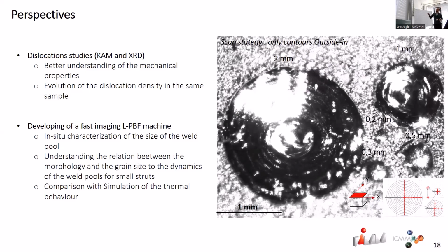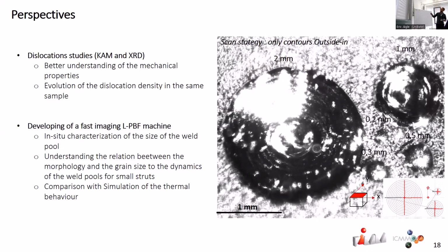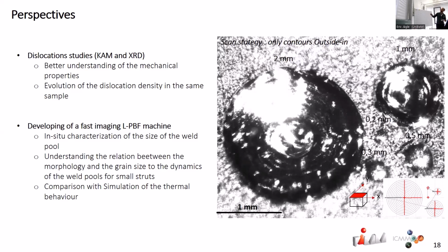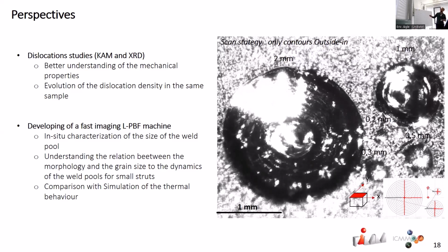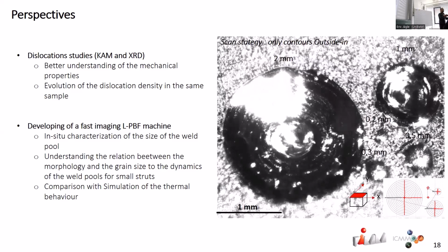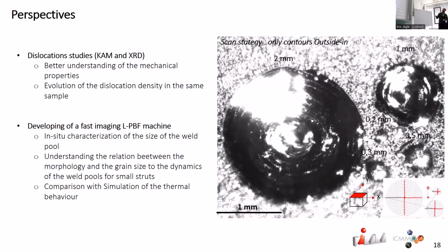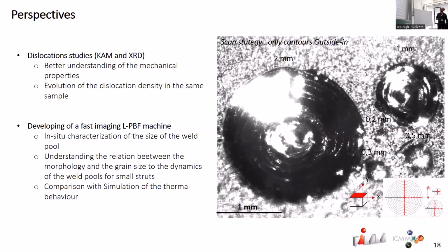And so you can see here a video. From here, we can see how the melt pool increases. It's to understand the relation between the morphology, the grain size, and the melt pools. And we're also running some simulations on thermal behavior to compare with what we're having here.